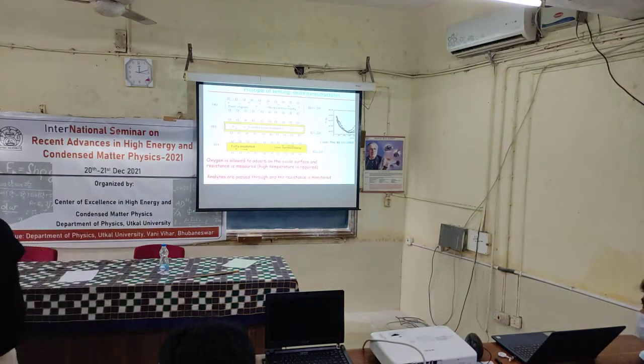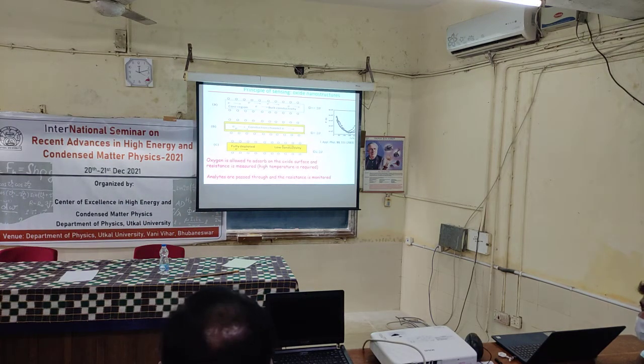Beyond 150 degrees centigrade, what is happening? Oxygen is absorbed on the surface of zinc oxide, but up to that point it is only physically absorbed. Once the temperature rises beyond 150 degrees centigrade, it is chemically absorbed. Oxygen has a tendency to take electrons, as it is on the right hand side of the periodic table. So it takes electrons from zinc oxide. It's tin oxide, doesn't matter, the principle is the same. If it is an N-type material, the conduction is through electrons, and the oxygen sucks the electrons from the oxide. So the number of charge carriers goes down. What do you expect for the resistance? Resistance should increase, and that's what is happening.